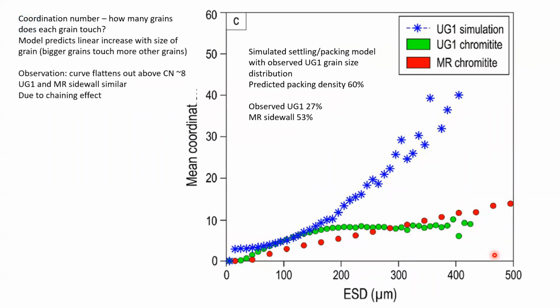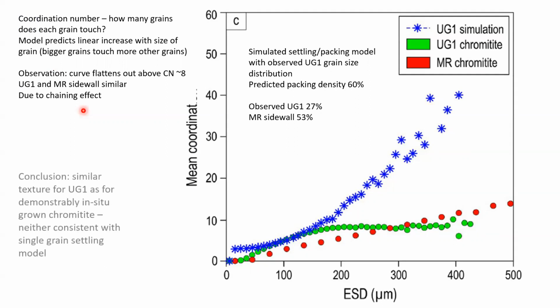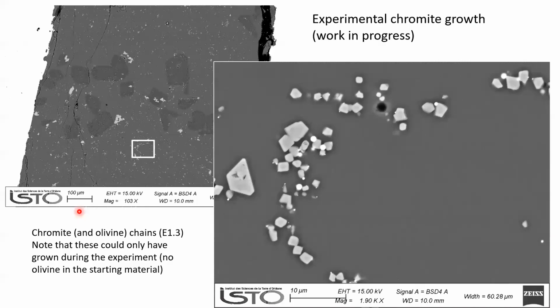So, the model predicts a linear increase with size in the grains. The observation is that the curve flattens out above a coordination number of about 8, and that the UG1 and Merensky Reef sidewall are similar. Why is that? It's because of this chaining effect. It's because the grains are not just randomly distributed. They're not just shaking around in a box. They're connected up to one another, and that effect reduces the coordination number. But the texture that we see in UG1 is similar to that for demonstrably in situ grown sidewall chromite. That's really the takeaway here.